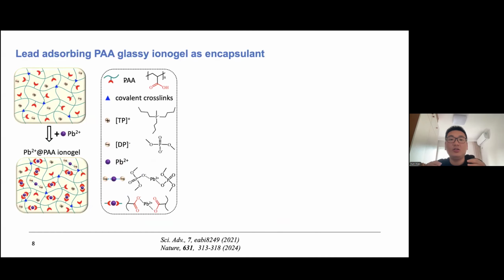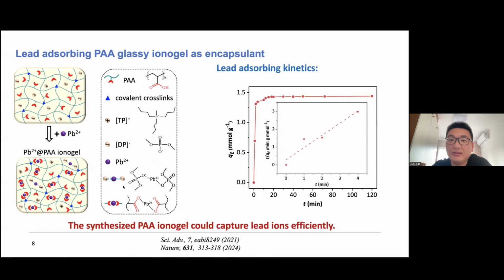So usually the gel is a polymer network that is swollen in an organic solvent. We first modify the polymer network with carboxyl groups. This carboxyl group can coordinate with the lead ions and capture them. And also we choose an ionic liquid with a phosphate acid group, which can also coordinate with lead ions. So both the polymer network and the ionic solvent can coordinate with the lead ions to give the lead absorbing property.